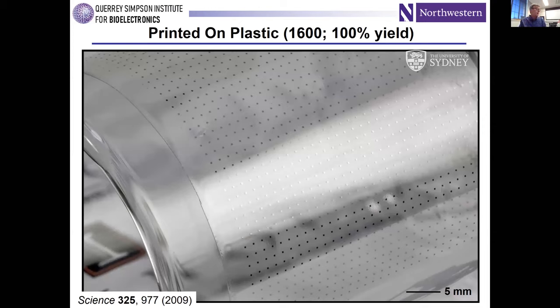So this is an example of silicon nanomembranes printed out onto a sheet of plastic, subsequently wrapped around a glass cylindrical support, just to show you the mechanical flexibility, which follows from the thin geometry of the substrate, the thin geometry of the semiconductor material. Also, it's really highlighting that linear reduction in the energy release rate with thickness of the semiconductor, because these elements are not popping off as you bend the substrate. So the adhesion is very robust. It's sort of that sticky characteristic that follows from the nanoscale geometry.